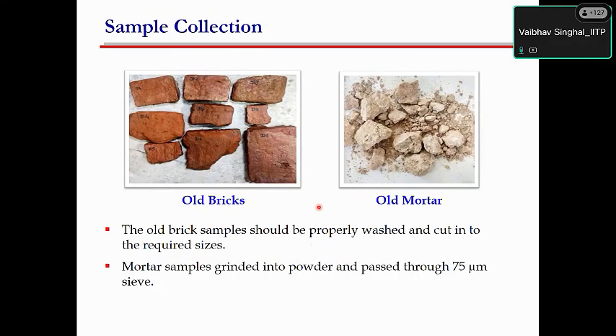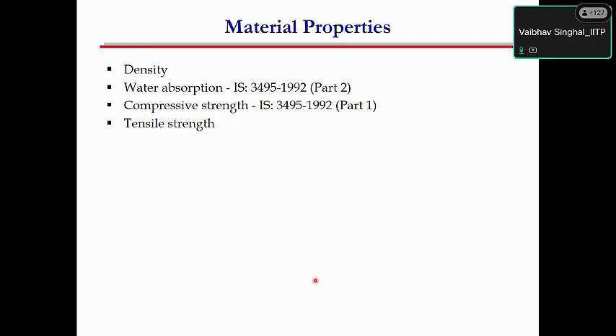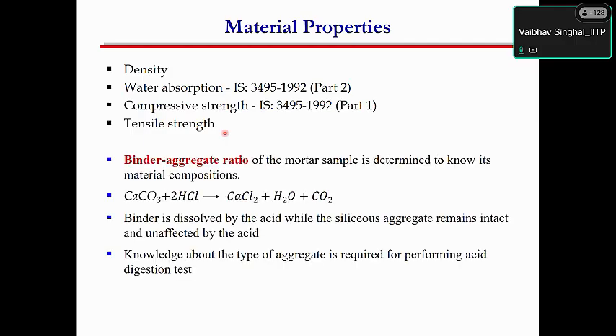So what we did, we got permission from ASI and collected some materials from the site. We collected some brick samples and some mortar samples, and these samples were properly washed. They were cut. The mortar samples were ground into powder and passed through a fine sieve of 75 micron. And then one can perform some of these tests. If you get a good size of bricks, you can cut them into small pieces and use them for different tests, like density, water absorption, compressive strength, and tensile strength also. And the mortar samples can be used to find out the binder aggregate ratio so that we can recreate those mortars in the lab.